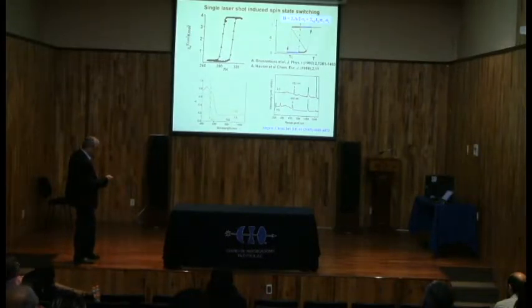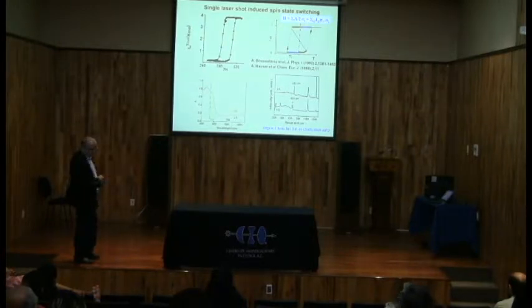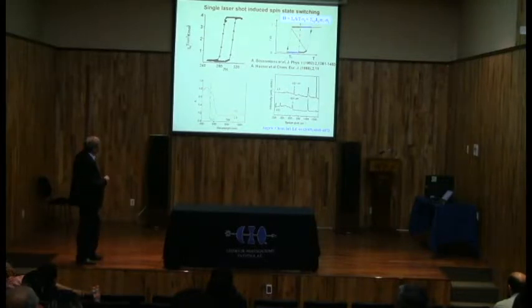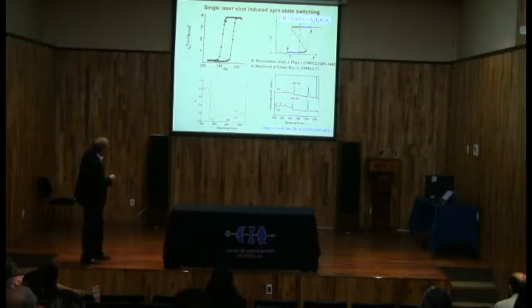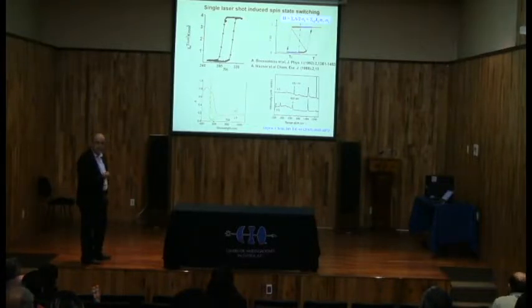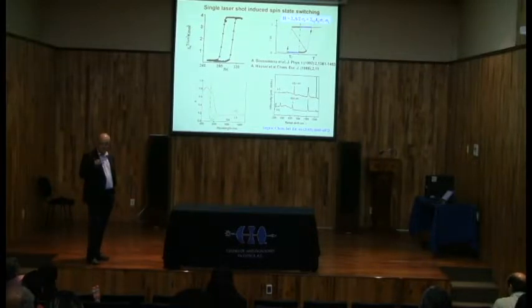If you go to the Hamiltonian I have shown you before, and look at systems where the cooperative interactions are strong enough, then if you analyze the hysteresis loop, you will see that you have 4 regions. You have this one, this one, this one, and this one. This region is the high spin form, spin 2, and it's metastable. And this region here is the low spin form, and it's also metastable. You have 2 metastable states with 2 different spins.